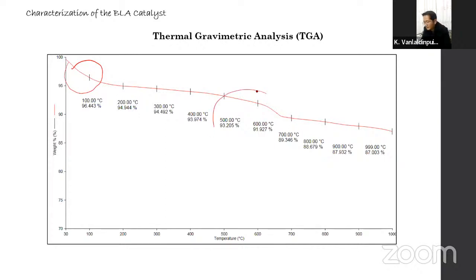Then we observed another weight loss at around 600 degrees Celsius. This may be due to the decomposition of carbonaceous materials. But if you look at it carefully, the overall weight loss is only about 13%. It demonstrates the thermal stability of the catalyst even at a very high temperature, above 1000 degrees Celsius, with only 13% loss.